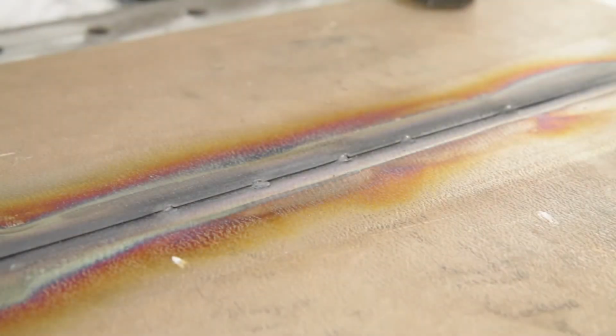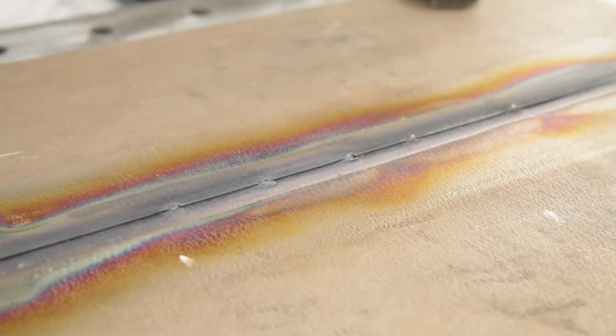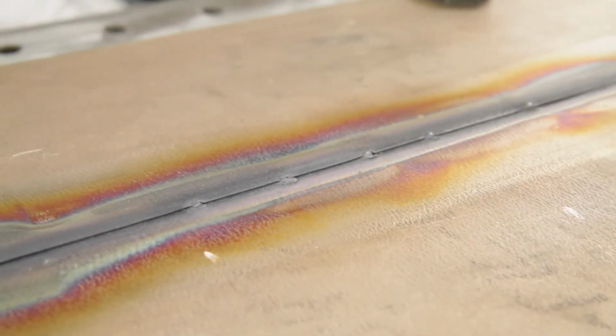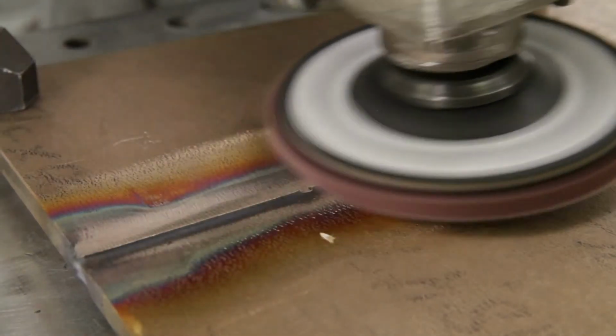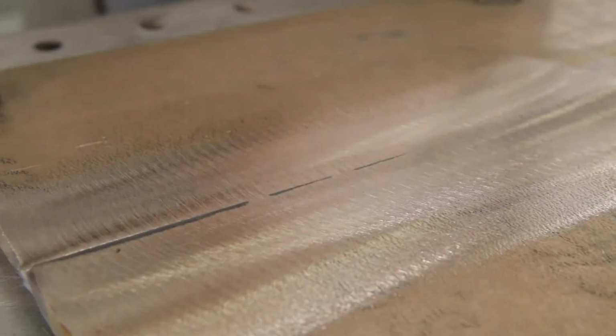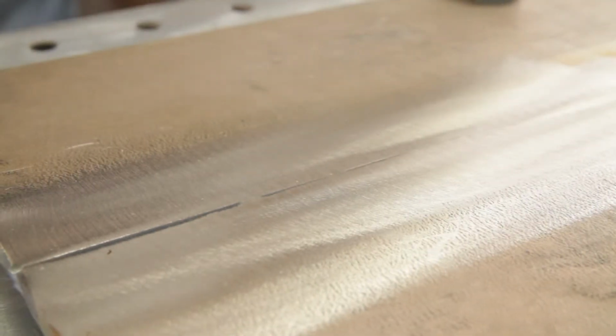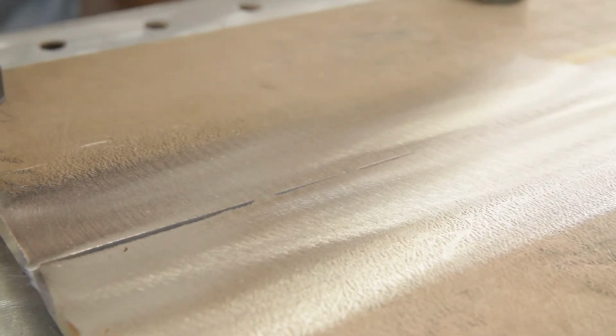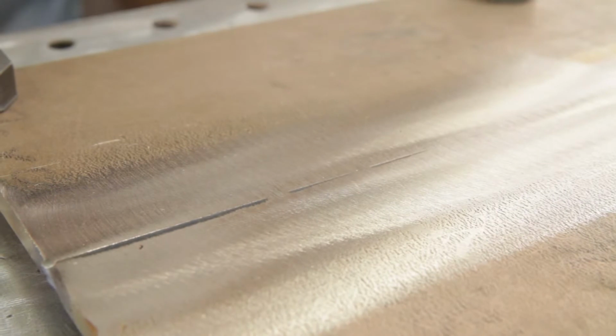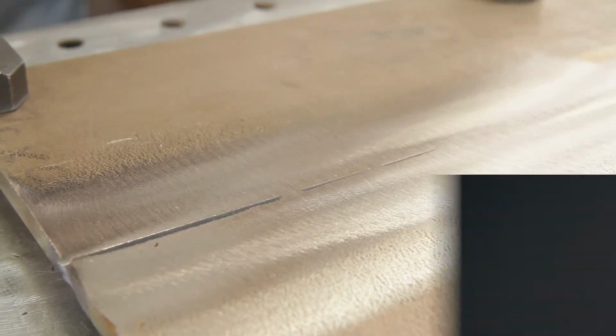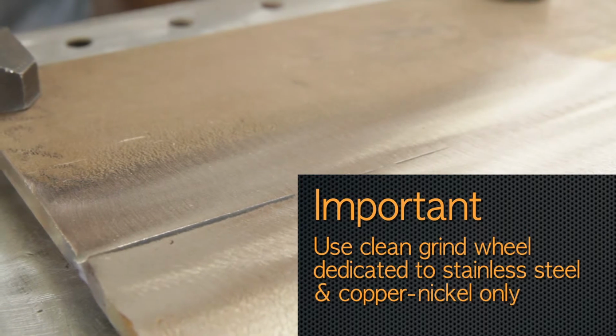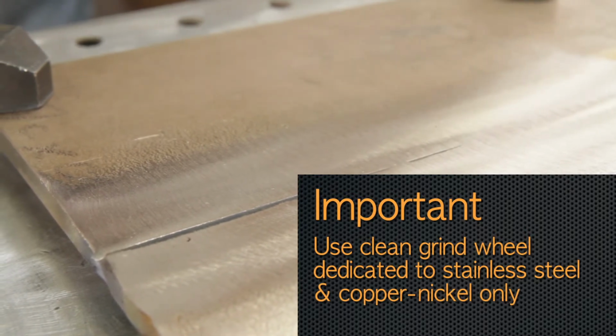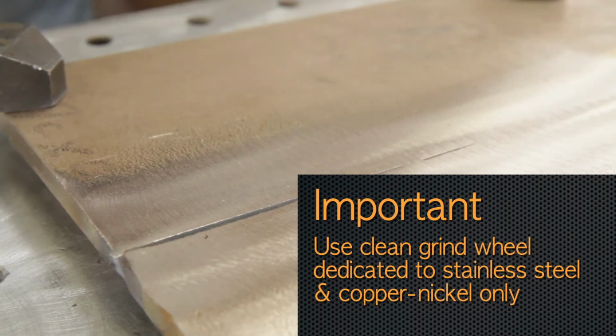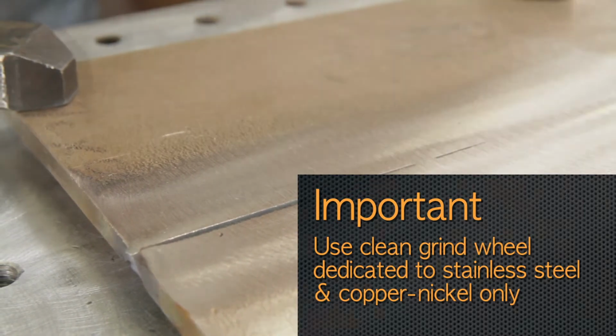Okay, we've finished the first side of this weld. We've turned the plate over to prepare the backside for the final weld. As you can see, the backside is oxidized because we did not use any kind of purge. So we will clean all the oxide off. As you can see, we've removed the surface oxide. We still have a little bit of black area corresponding to the root face of the back. We're going to grind that out now with a hard wheel, again paying attention to the fact that we only use wheels that have been used on stainless steel or on copper nickel. Never use a wheel that's been used on carbon steel.